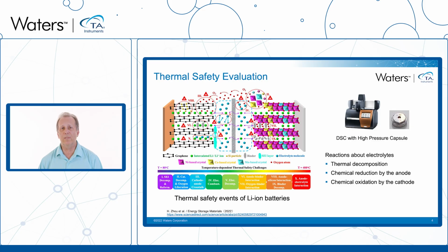Further up in temperature, there's the shrinkage and decomposition of the polymer separator, which I spoke about. Loss of that will induce short circuits through the battery, thereby increasing chemical reactions and increasing the heat. And then on the high temperature end, we actually have degradation of, say, the electrolyte or the actual battery components that are sitting on the metal foils, the copper or the aluminum metal foils. When we use DSC to study some of these reactions, the materials are typically put in high pressure capsules. You can see that there's an image of one right next to the DSC here. We put these in high pressure capsules so that as the heats are evolved and as materials are decomposing, they're not allowed to escape through the pan, and thereby we capture the full heat of the decomposition or whatever chemical reaction that's happening inside of the pan.